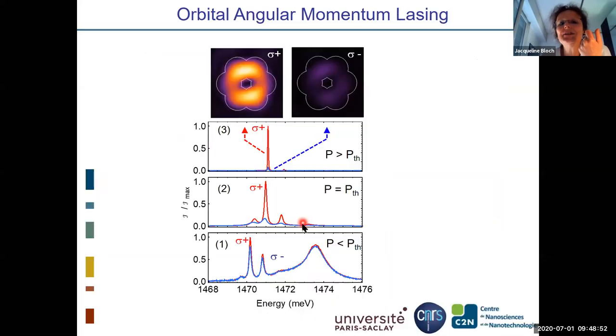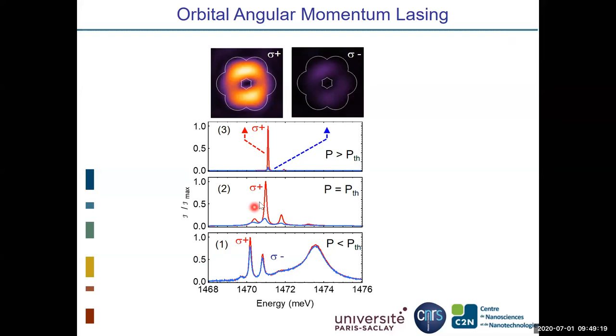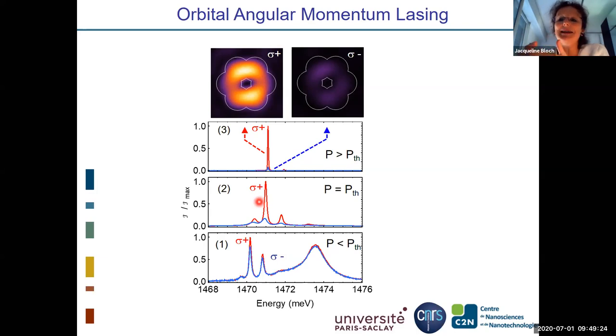Typically the relaxation time to populate, so the rise time of the emission, if you were to measure it in a time resolved way, what you would see is that the rise time of the luminescence is typically a few picoseconds. So it means that the relaxation is faster than a few picoseconds, especially when you are close to threshold. So it means that the depolarization is of the order probably of a few 10 picoseconds.